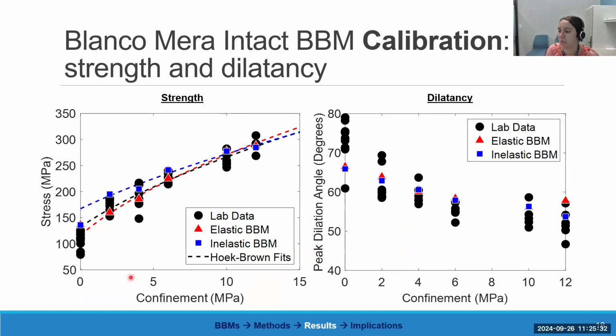So in all of these figures, we've got confinement plotted here on the x-axis. So I ran 6 different confinement level compression tests. First, there's a UCS or an unconfined test here with 0 confinement. And then I ran 5 different triaxial simulations ranging between 2 and 12 megapascals of confinement. And so in all these plots, the lab data is plotted as the black circles, and then the results of the calibration for the elastic block BBM are plotted as the red triangles, and the inelastic block BBM results are the blue squares. And then we've got some Hoek-Brown fits just to help us look at trends.